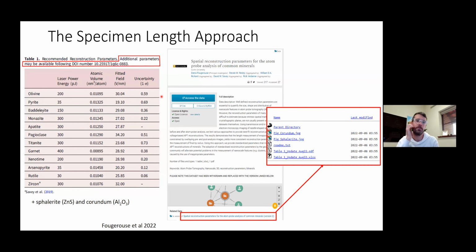Yeah, so that's a problem we encountered and thought about only moderately. It is true that the field value will change in data sets, and that was apparent especially in oxides. No, in silicates, I can't remember which ones, but if you measure the radius of the specimens at the end of the analysis, you can calculate the field value from the voltage, and it is very different from the one we calculate from the specimen length approach. So yes, it is apparent that the field value changes with the voltage and the radius. But the way we like to think about it is that we do this.